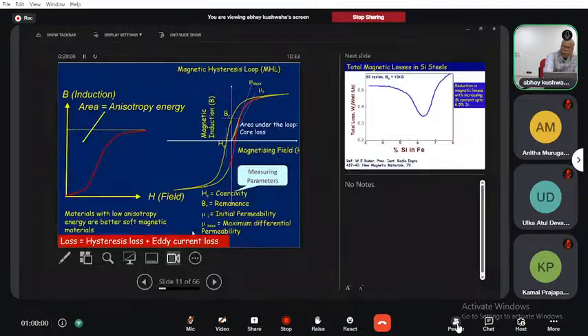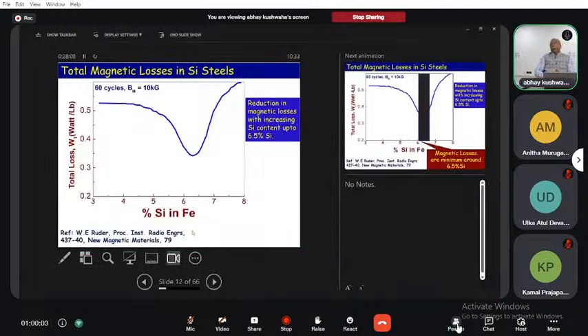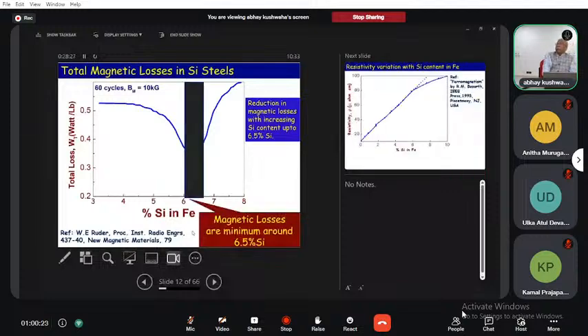Now, if we consider the silicon steel, if we go on increasing the silicon, you can see the total loss, which is coming, is reducing as we increase the silicon, and it becomes minimum. This loss is minimum when it is about 6.5%.